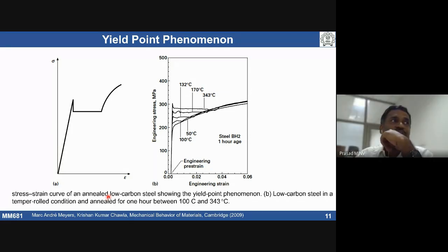Okay, so what you are talking about, this is my stress strain curve. If I do not do any skin pass rolling after annealing, and I conduct a stress strain tensile test, I get this kind of stress strain behavior. This strain is about 1 to 2%.